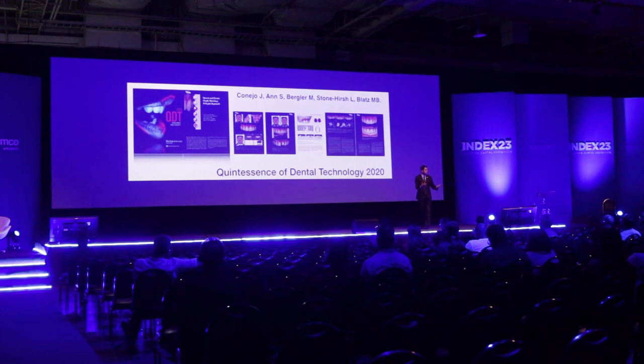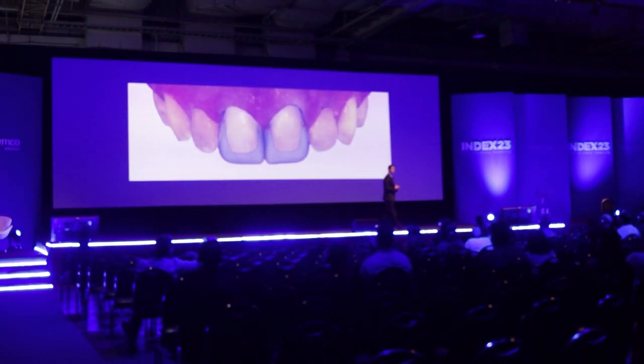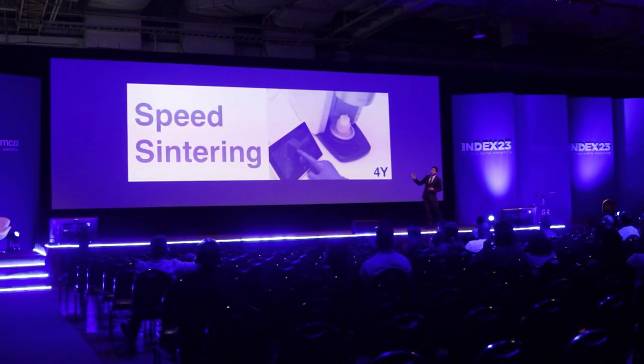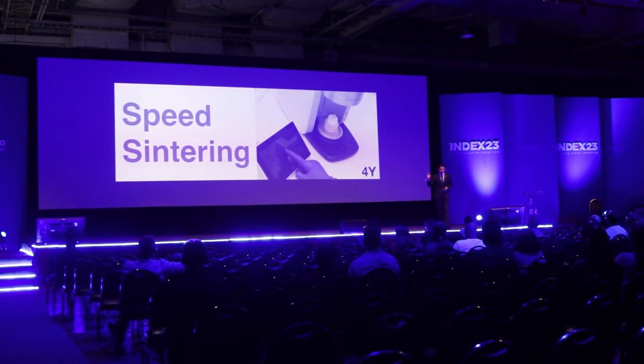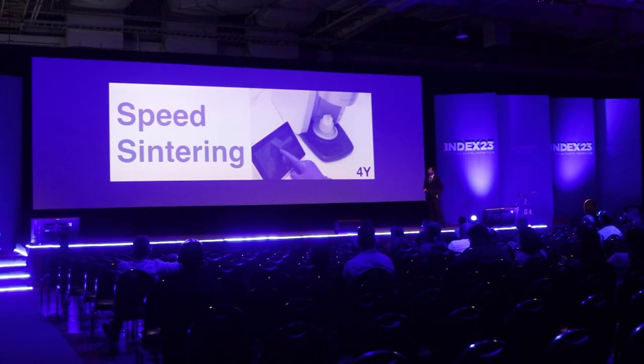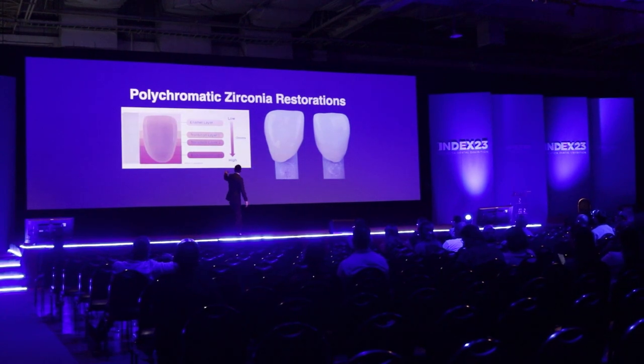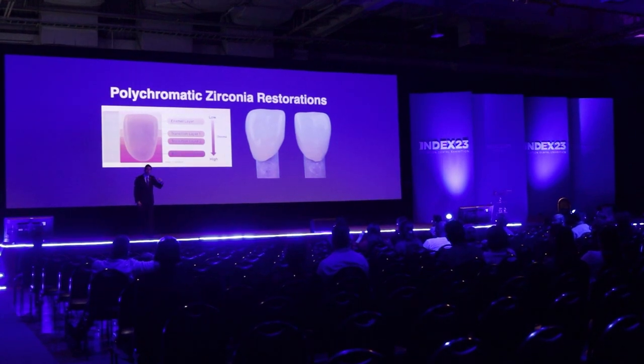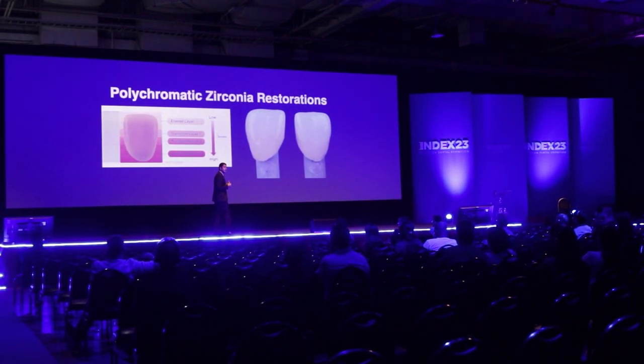In 2020 we started publishing our work using monolithic zirconia restorations in QDT 2020. This case involves endodontically treated teeth — I'm scanning, designing, and using Katana Zirconia STML, super translucent multi-layer with 4% yttria. I can design, mill, and also speed-sinter this type of zirconia, even faster than lithium disilicate, which makes production very quick. The aesthetic benefit: these zirconias are polychromatic, with more dentin layer at the bottom and more translucency going up, so the restoration is already multi-chromatic without additional painting. The color is intrinsic, so it will be maintained for a longer period of time.